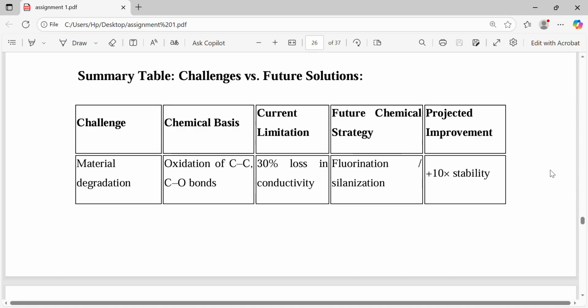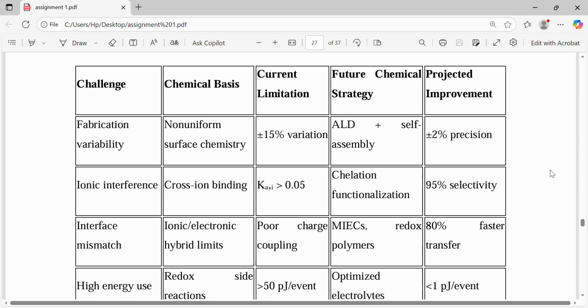Challenge: material degradation. Chemical basis: oxidation of carbon-carbon and carbon-oxygen bonds. Current limitation: 30% loss in conductivity. Future chemical strategy: fluorination, silanization. Projected improvement: plus 10 times stability. Fabrication variability: nanoscale non-uniform surface chemistry, plus or minus 15% variation. Future strategy: ALD plus self-assembly, plus or minus 2% precision.